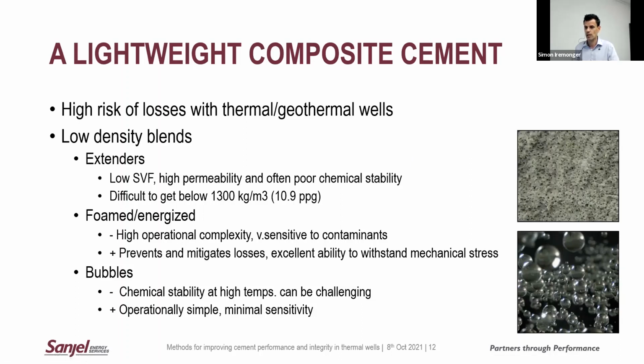Certainly, you can go down the conventional route of using typical extenders, but typically you have high permeability and poor long-term properties there, and it's difficult to get cement densities below your 1,300 kilograms per cubic meter or 11 pounds per gallon. Foam cements have already been kind of discussed a little bit. They've got a number of advantages, certainly exceptional at preventing and mitigating losses and excellent ability to withstand mechanical stresses. But on the other side, they do have a high degree of operational complexity. It's a lot of extra equipment out there, and they can be quite sensitive to contamination, and you need to be very, very vigilant with your cement blend design to ensure that you've got a robust slurry system there.